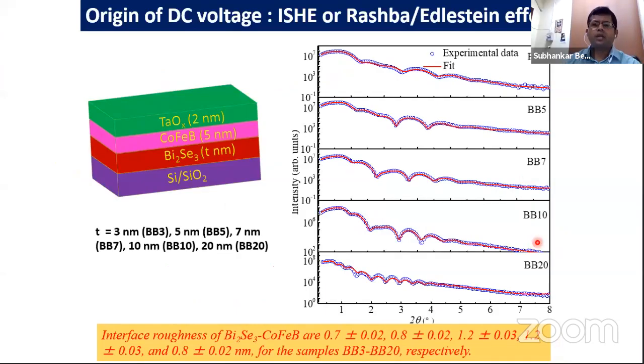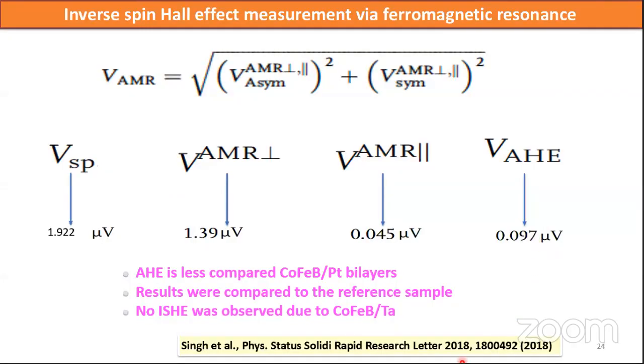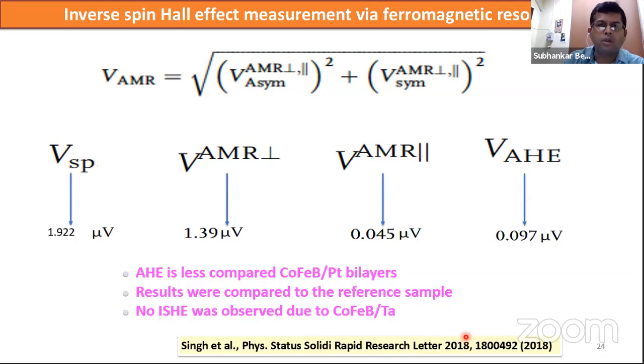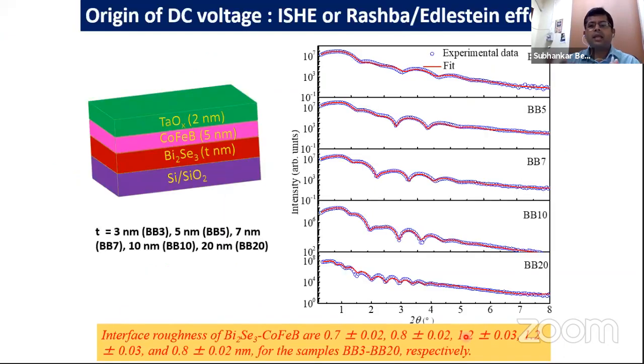Yeah. So now we wanted to, of course, that paper we published basically 2 years ago, and Braj was very happy that this paper was one of the top downloaded papers of PSS Rapid for the year 2019. And then we tried to understand a little bit more about the bismuth selenide we have prepared, whether it's more of a surface effect or more of a bulk effect. So the inverse spin Hall effect is more bulk, and the Rashba-Edelstein effect is more surface.